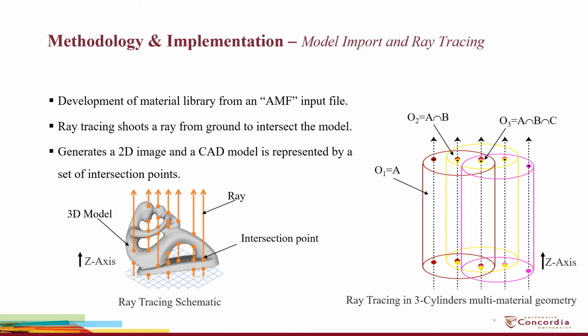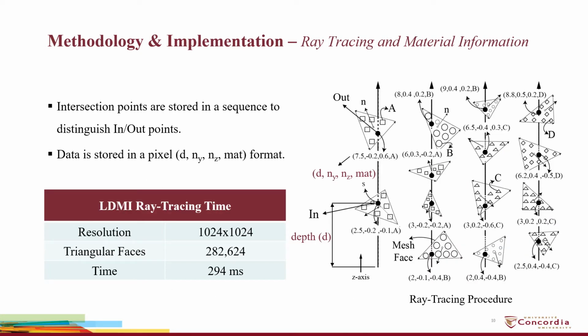Ray tracing is a simple technology in which we shoot a ray from an origin to intersect the 3D model and generate intersection points. And that is how an input 3D solid mesh is converted into a set of intersection points. Moving on, the intersection points are stored in an ordered manner to distinguish between in and out intersection points for each material. For each intersection point, we store 4 values of information, which are depth, normal in y and z direction, and material of the triangular face intersecting the ray. With a resolution of 1024 and a mesh of approximately 282,000 triangular faces, parallel ray tracing only takes about 294 milliseconds.